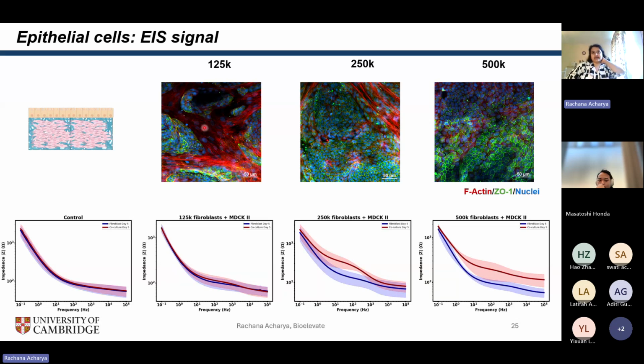And in fact, as you can imagine, if the fibroblasts have not completely covered the scaffold because they have not completely grown, that's where you find that the epithelial cells do form barriers, but in very local regions. So this is actually an image in the same plane. You can see that wherever there was space from the fibroblasts, where they did not cover the scaffold, that is where I have this barrier formation. But it's practically the epithelial and the fibroblast cells existing in the same monolayer.